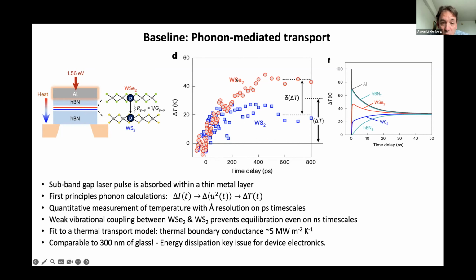So here are the experimental results, plotting the change in the temperature of each of these two layers. We're zooming in on first the Bragg peaks associated with the WSe2, then with the WS2, and we can independently plot the layer-specific temperature in this response. And what you see are a couple of things. First of all, the response is quite slow. The axis here is in hundreds of picoseconds.